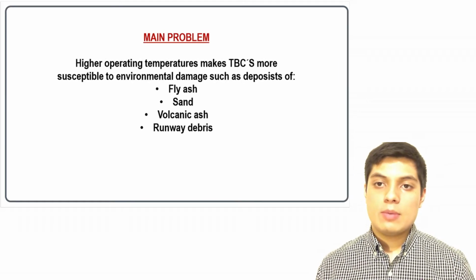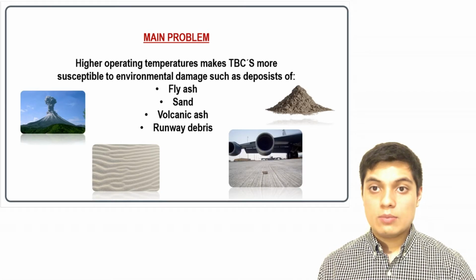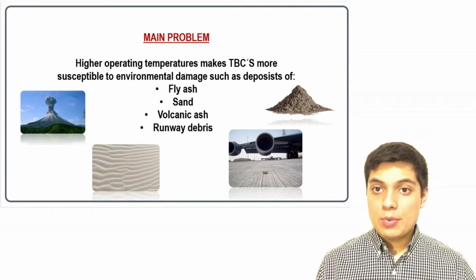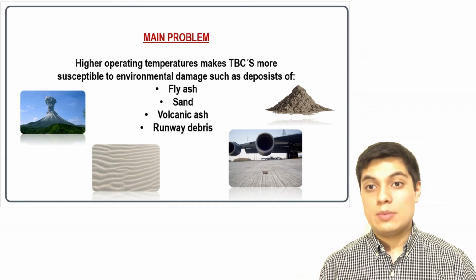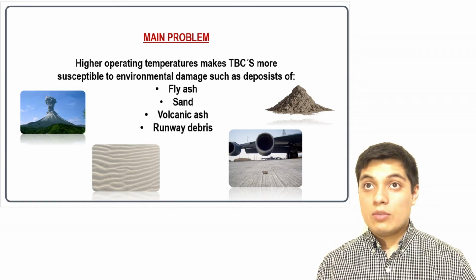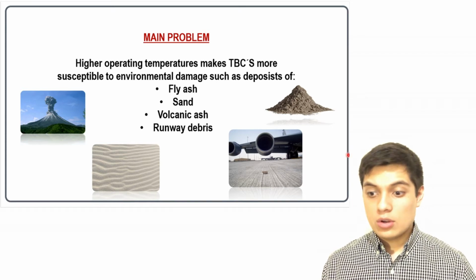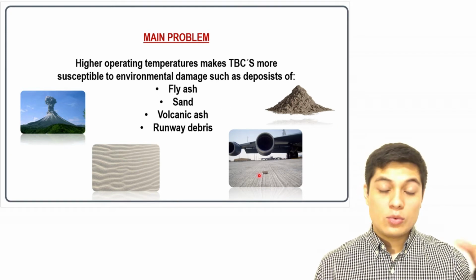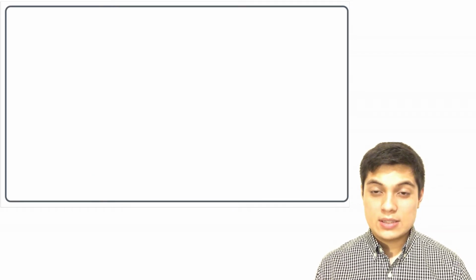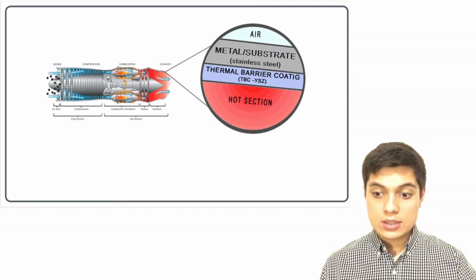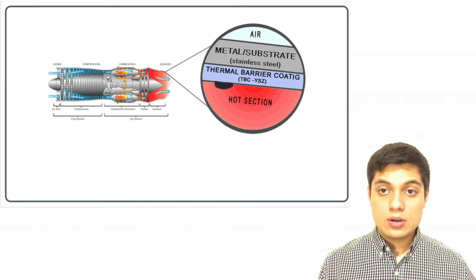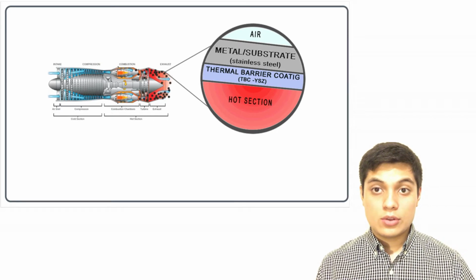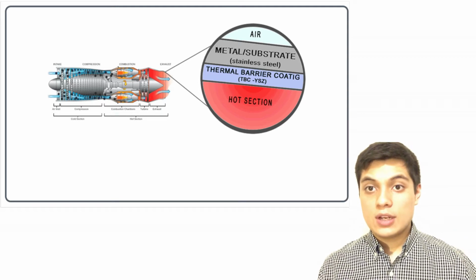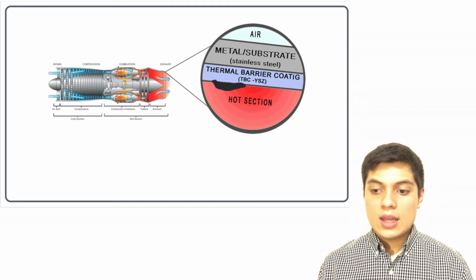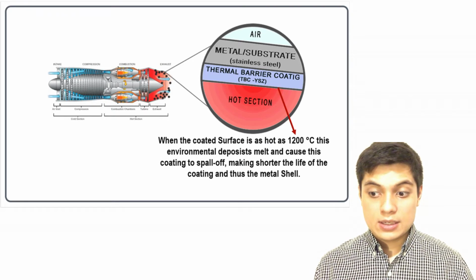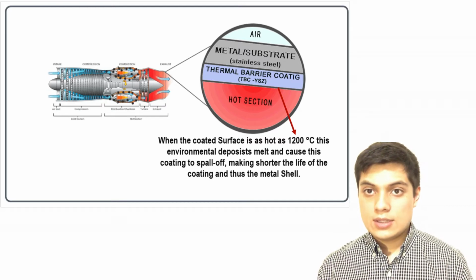The main problem of these yttria-stabilized zirconia coatings is that when they are operating at higher temperatures, they become more susceptible to environmental damage from materials or particles composed of fly ash, sand, volcanic ash, and runway debris. What occurs with these materials that causes the damage of these thermal barrier coatings? Here we can see an animation of how these particles enter the chamber of the turbine, and when they arrive at the hot section, they melt. It is around 1200 degrees Celsius when they melt.